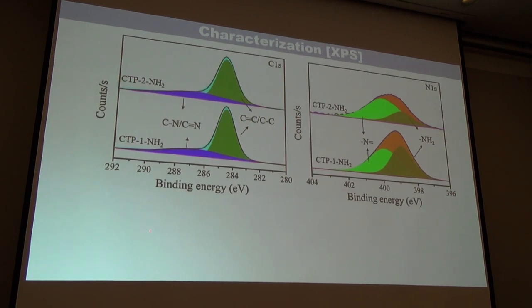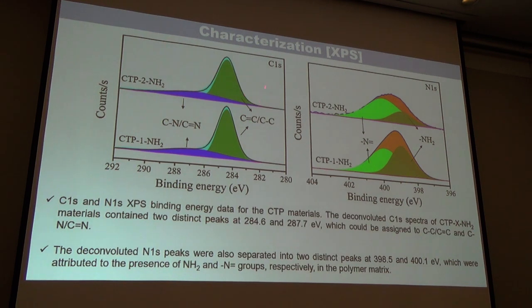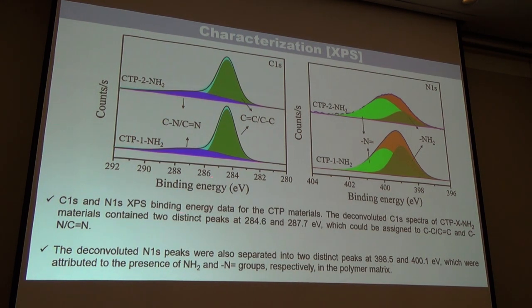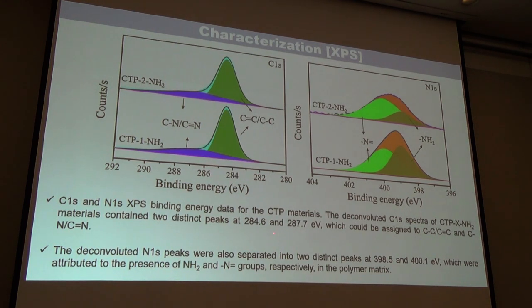Further, the chemical state of elements in the polymer is analyzed using XPS analysis. Here, the C1s deconvolution shows two distinct peaks at 284.6 and 287.7 electron volt. The one at 284.6 could be ascribed to C=C and C-C binding energies, and the one at 287.7 could be ascribed to C-N and C=N binding energies. Similarly, the N1s shows two distinct deconvoluted peaks at 398.5 and 400.1 electron volt.